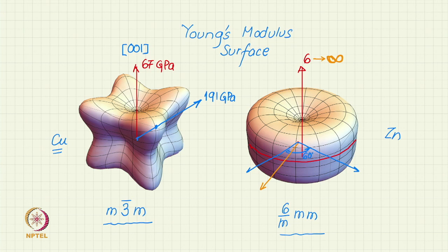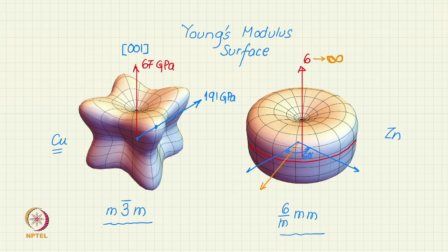Isotropy includes 6-fold symmetry, so there is no violation of Neumann's principle. But this is an example where the symmetry of the physical property not only includes the symmetry of the point group of the crystal but also has more symmetry. Similarly, 6/mmm is supposed to have only 6 vertical mirror planes, but in this surface any vertical plane passing through the symmetry axis of the crystal is actually a mirror plane — it has many more mirror planes than indicated by the point group. Thank you very much.